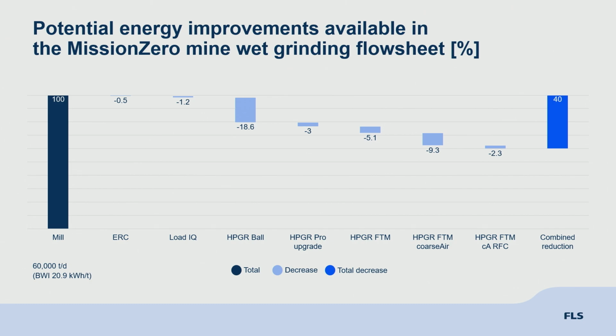And then on our SAG mill, we put Load IQ, an acoustic system with PSD control at the back end, and we could reduce energy by a further 1.2%. But if we actually removed that SAG mill and replaced it with an HPGR, we could get an 18.6% reduction. So that really was the biggest change.